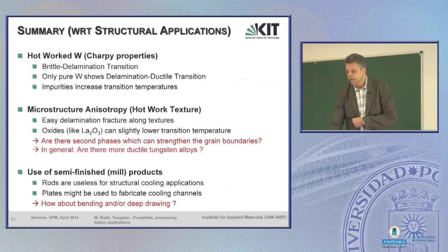So hot worked tungsten shows a brittle delamination transition. Only pure tungsten shows a delamination ductile transition in the case of rods, and impurities increase transition temperatures a bit. And the microstructure anisotropy of hot worked texture is that we see easy delamination fracture along the textures. Oxides or carbides like lanthana can slightly lower the transition temperature, but also, depending on the case, increase it.